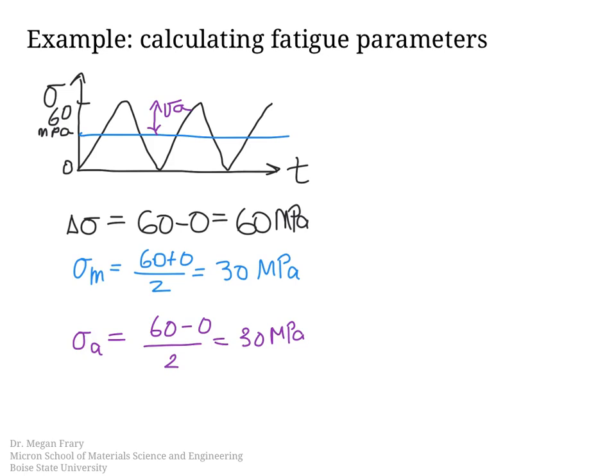And the last thing is to calculate r, the stress ratio. So in this case, we find that the value of r is equal to 0, and it will always be equal to 0 if we have essentially a 0 to full tension loading situation. So if it starts at 0, it doesn't really matter how high up the stress goes, that value of r will always be equal to 0.